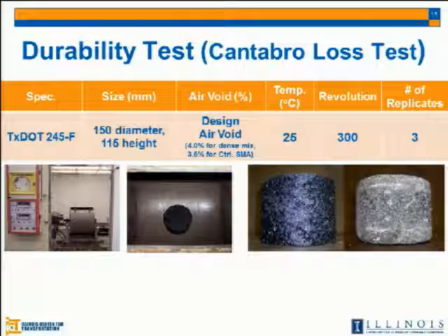The third or fourth test is the durability test. According to the Texas DOT specification, first we made the gyratory samples to have the 115 height and design air void. So we measured the weight of this gyratory specimen. And then we put this gyratory specimen in the LA abrasion machine without steel ball. And then we rotate 300 times, then take it out, and then measure the weight of the specimen. And then calculate the loss of the materials.